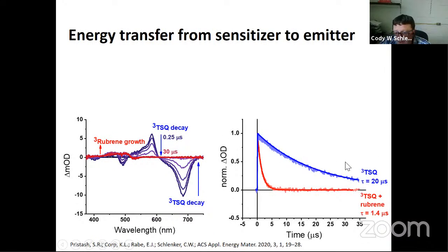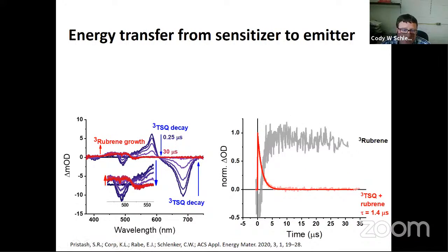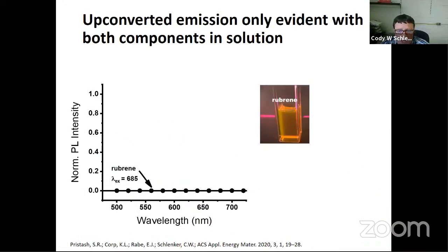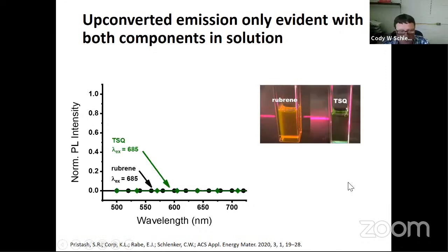And so here you see the native lifetime of our triplet for our dye molecule. We add rubrene and it quenches that. We can see the growth of the rubrene triplet as well. You pair these things together. So here is rubrene just by itself. We see no fluorescence from the rubrene whatsoever if we excite it in the red region.